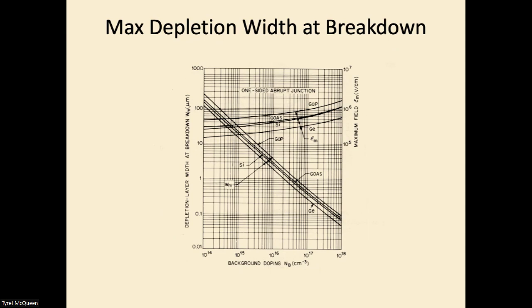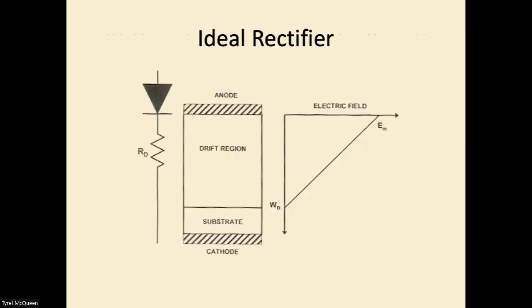We remind you that the maximum depletion width at breakdown will be a function of doping. So at, say, breakdown at a doping of 10 to the 15th, there will be a breakdown voltage at that doping. This is given by the maximum field, and this nomograph shows you what the maximum depletion width is for silicon at breakdown. So 100 microns at 10 to the 14th, and the maximum field over here would be given by the nomograph. Okay, going back, reminding you this is our ideal rectifier.